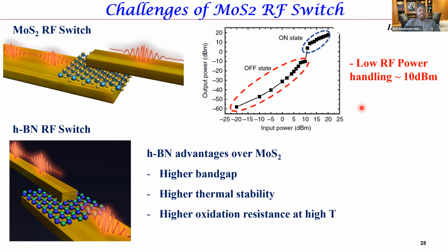Well, switch the material - hBN is a much more thermally stable material. It has a higher bandgap, it can endure higher temperature, and it has greater oxidation resistance, because when you send high power through these materials, the local hotspot can be much higher than the ambient, so oxidation effects cannot be ruled out. So hBN is more attractive for this.